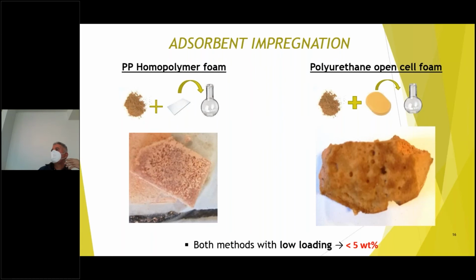What's the problem that we have found with this kind of impregnation process? It is that if we measure the ratio or the quantity of MOF impregnated into the foams, it is very low. We have not achieved more than 5% by weight of MOF inside the foam. Of course, this low quantity limits the performance of acetic acid absorption a lot. We need to find new technologies to increase the interaction or to increase the quantity of MOF that we can include in the cells of the foams.